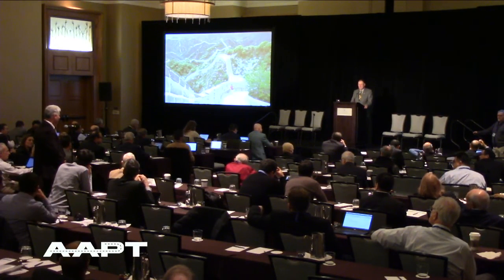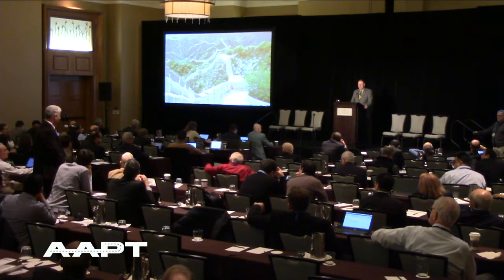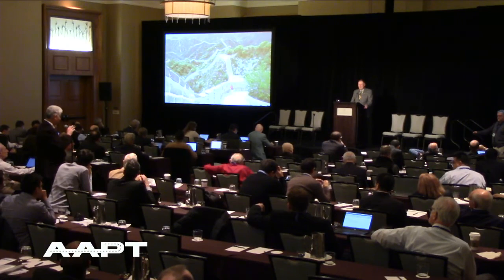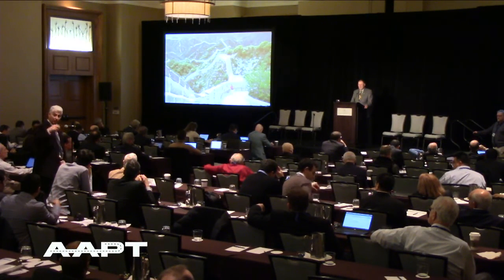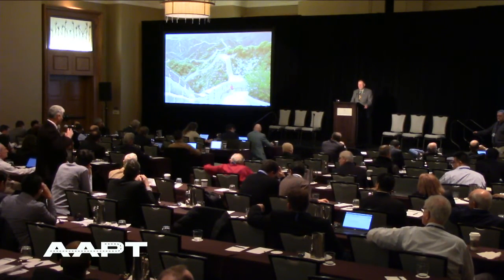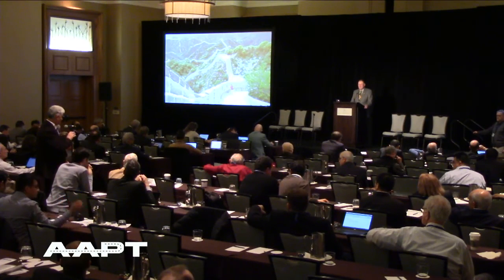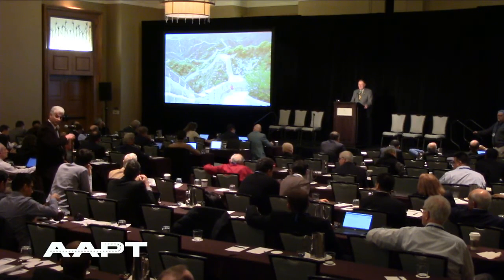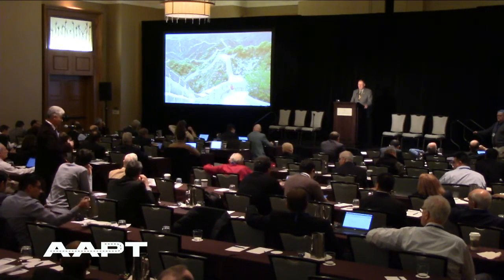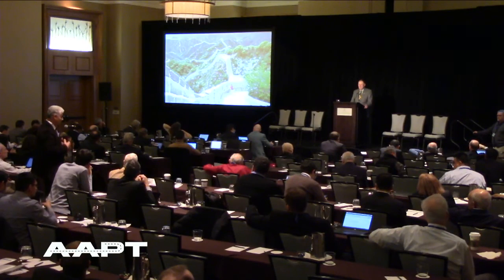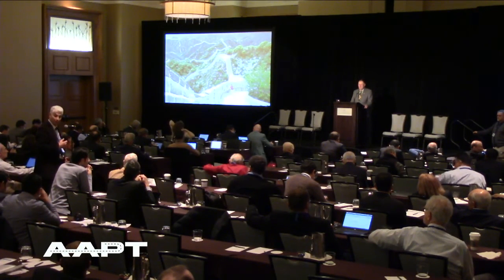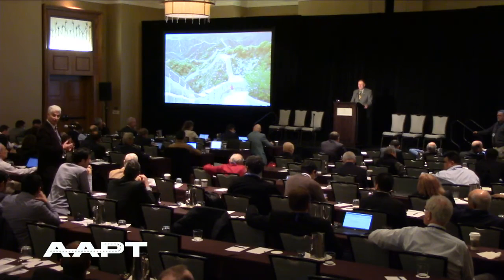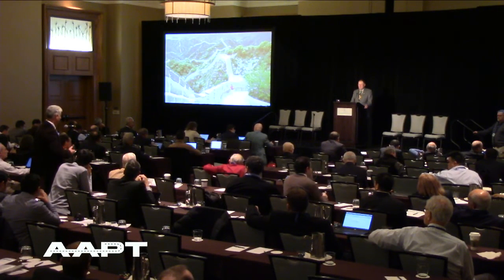Jerry, I don't know if you recall, but we also did some analysis on those sections to look at the strain magnitudes we'd calculate versus those that were being measured. And the trends were absolutely consistent with the measurements thereabouts. I mean, you're going to get some scatter because of the daily variation in temperatures and things like that. But the trend sort of confirmed that those strain gauges were doing what we wanted and the pavement was behaving as you expected to see it.